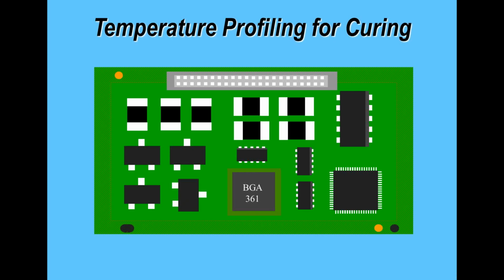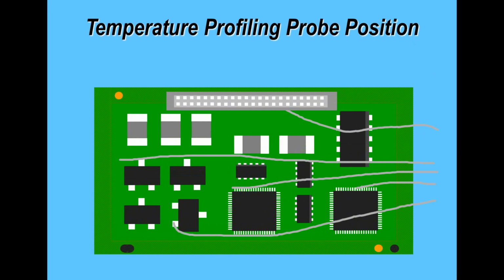Now, if we're looking at a board that's got all the parts that I've previously mentioned, but also includes through-hole for pin-in-hole intrusive reflow, then you've got to monitor the connector as well. So here I'm monitoring underneath the connector. I would normally always monitor underneath the connector in the center of the connector, and the reason being, that would generally be the coldest part. The paste is normally put on the top side of the board, you insert the connector, so that's what you're reflowing. You don't monitor the opposite side of the board, unless of course that's where you're actually adding your paste to the assembly. So normally underneath the connector and in the center of the connector. In the example I show you, in theory, the ends of that connector would get hotter quicker than the center area.